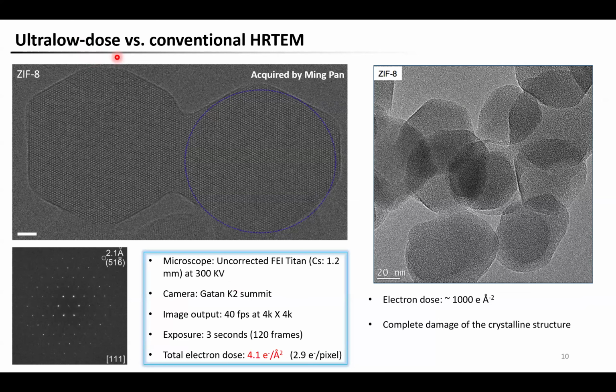So combining these methods with the new camera, we have established the so-called ultra-low dose HRTEM technique, which allows us to acquire images with an electron dose as low as several electrons per square angstrom. And this ensures the structure integrity of highly beam sensitive materials like MOFs. So using this technique, we got this image from the same MOF material discussed earlier, whose structure was completely damaged by conventional HRTEM, as you may recall. Okay. So this comparison, I think, very well demonstrates the power of the ultra-low dose HRTEM.